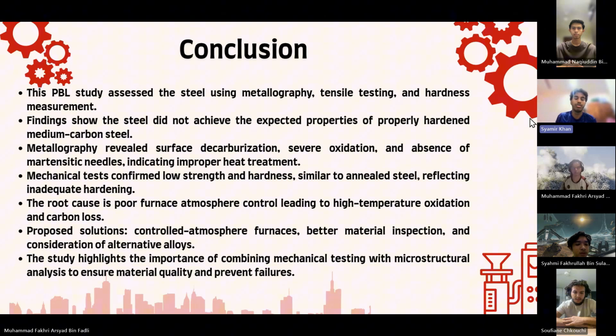Okay, now to conclude our PBL. In this study, the steel sample was evaluated using metallography, tensile testing, and hardness measurements. The results indicate that the steel did not reach the expected properties of a properly hardened medium carbon steel. Microscopic analysis showed severe surface oxidation, decarburization, and the lack of martensitic structure, while mechanical tests revealed lower than expected strength and hardness.